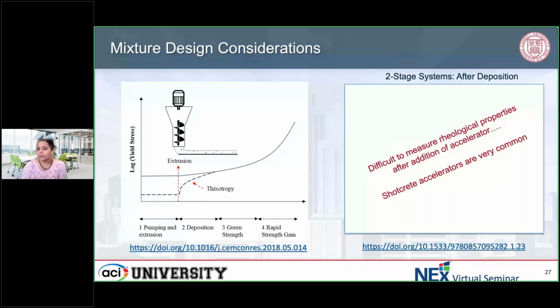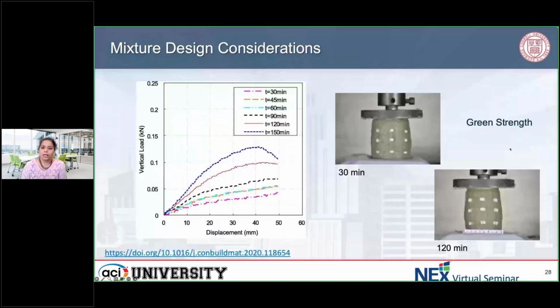For that transition to happen, shotcrete accelerators are very commonly used. You use the same accelerator that you would use in shotcrete application, but you inject it at the nozzle. Since you cannot use a rheometer to measure that transition, what you could do is measure the green strength of concrete. You take the material after you've injected the accelerator. You could use this for both one-stage or two-stage systems, and then you can make a cylinder. There's obviously no ASTM standard for this, so people have developed this technique.